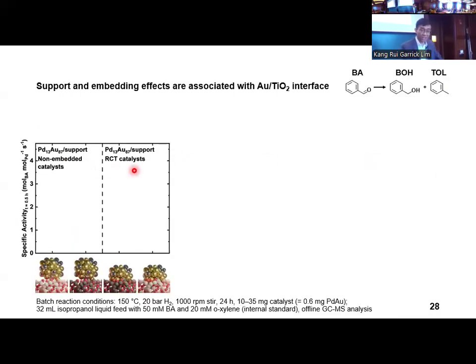The non-embedded and partially embedded RCT catalysts were tested using benzaldehyde hydrogenation as our probe reaction, building on our earlier work. All the catalysts were very selective to benzyl alcohol and stable after reaction, which allowed us to compare differences in the intrinsic catalytic activities alone. We first compared the non-embedded catalysts to determine the effects of support chemistry. The silica-supported catalyst was moderately active due to palladium ensembles on the nanoparticle surface that activated hydrogen and bind to benzaldehyde. A slightly higher activity in the titanium-supported catalyst suggests additional benzaldehyde binding at this nanoparticle titanium support interface.